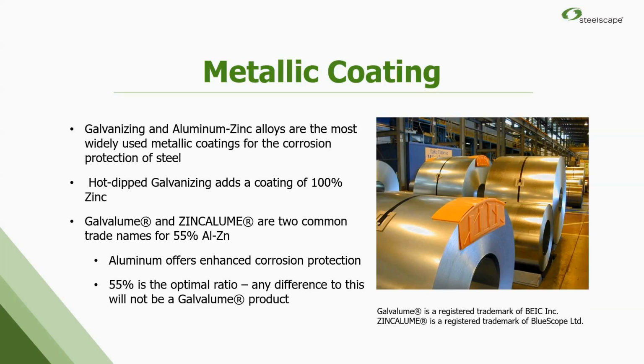The addition of aluminum gives you added corrosion resistance. So much better performance long term, especially in severe environments. That aluminum becomes very inert and doesn't allow much corrosion to take place. And that 55% is an optimal ratio that was developed 50, almost 60 years ago now. The Galvalume name and the Zincalume name are both registered trademarks. There's a licensed company called BEIC that licensed that Galvalume product. You cannot use that name unless you are licensed and are adhering to the manufacturing quality expectations of that product.